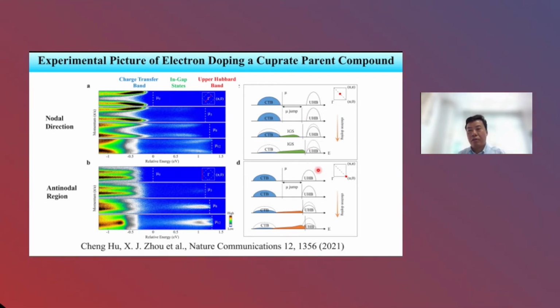Okay, I think if you compare with the theoretical proposals proposed a long time ago, it is quite different, because at that time, people thought that if you dope the system, usually the in-gap states are limited to some small region. But actually, in the real case, we can see that the spectral weight spreads all over the entire cuprate region. Okay, so this is different from the usual thinking that the in-gap states are limited to some narrow region. But actually, it spans over the entire cuprate region. So this is the work we have done on doping the Mott insulator by electrons.